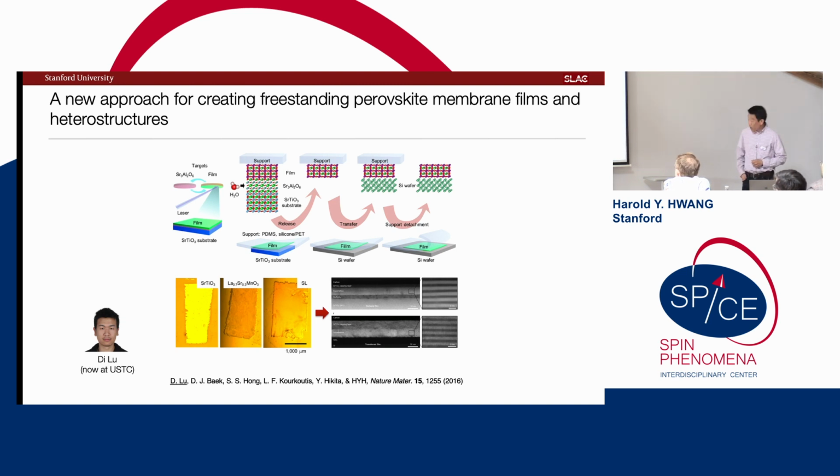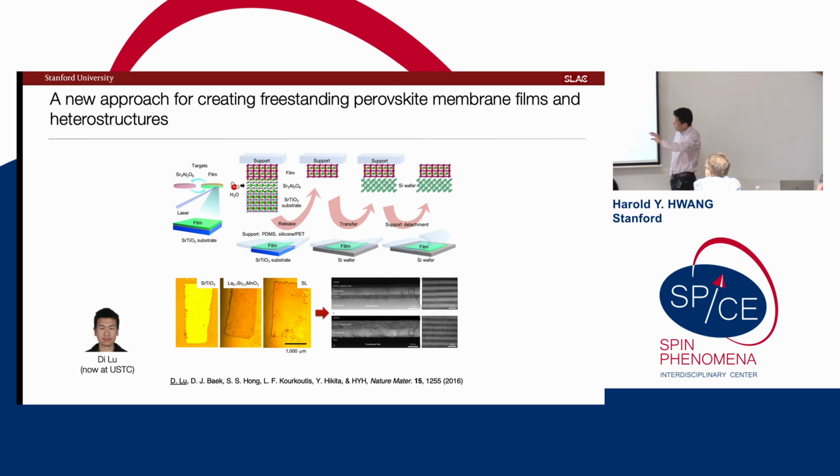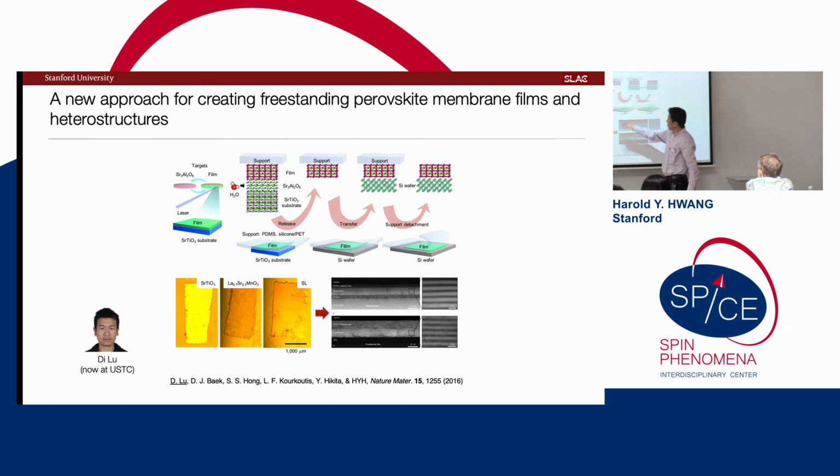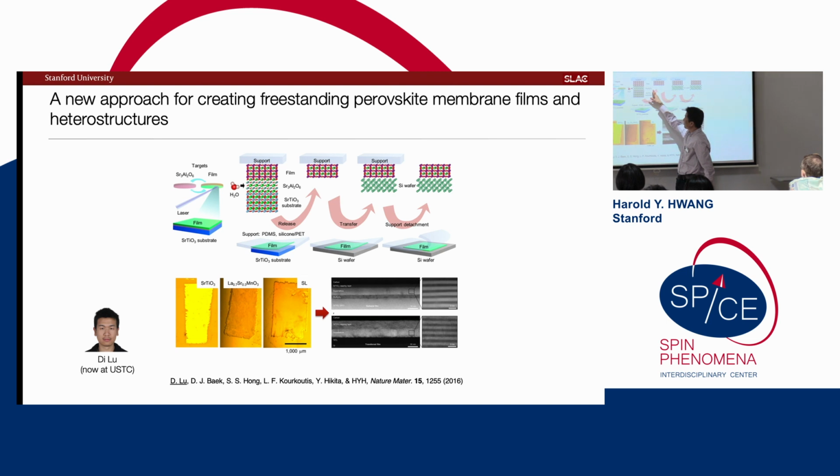So that's the story in our nice dry UHV chamber. This is just some other layer to grow. But after we grow some heterostructure, this epitaxial layer can just be dissolved away in room temperature water, piggybacking off the 2D world. Using various elastomer or polymer supports and masks, just dunk the whole thing in water, dissolve this out, and then we can transfer these membranes to other places.